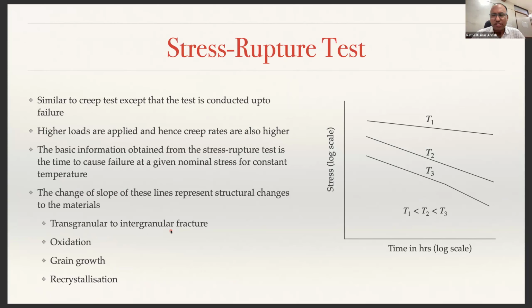And there is another test. Previously, we have done the creep test. There is another test called the stress rupture test. What does this stress rupture test do? It is similar to the creep test, except that the test is conducted up to failure. You conduct the test up to failure and measure the stress at which the failure happens. So here what you do is you apply higher loads. As a result, the creep rates are also usually higher.